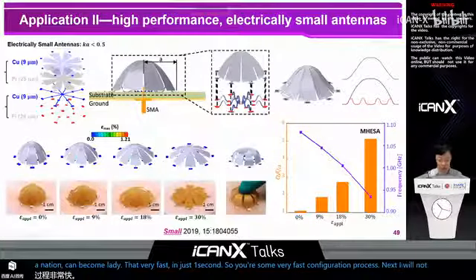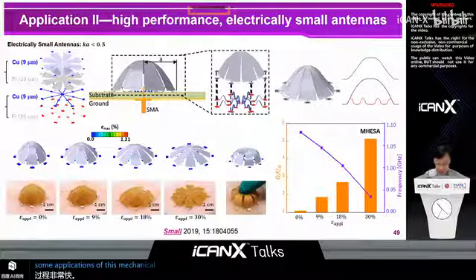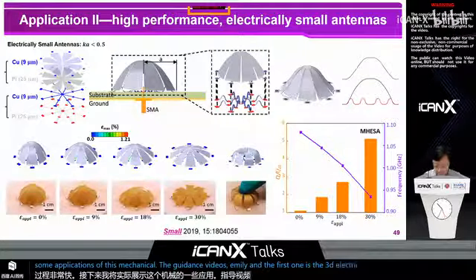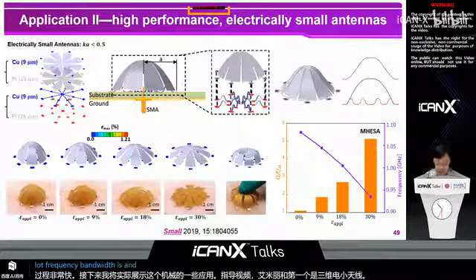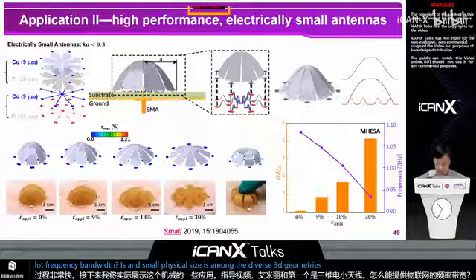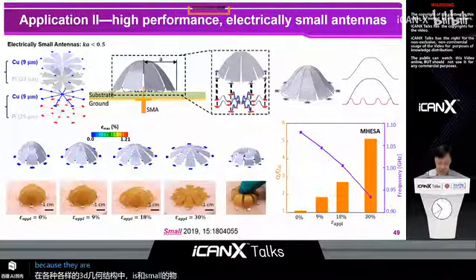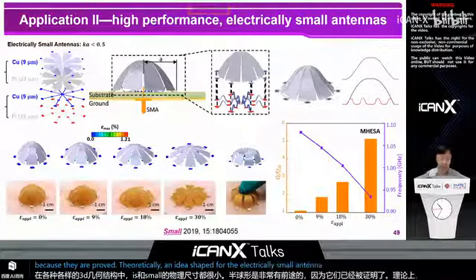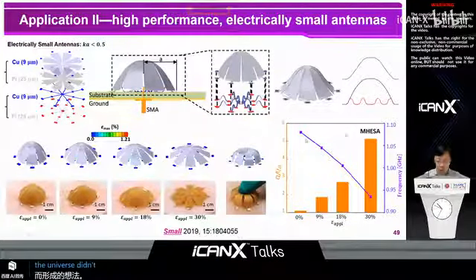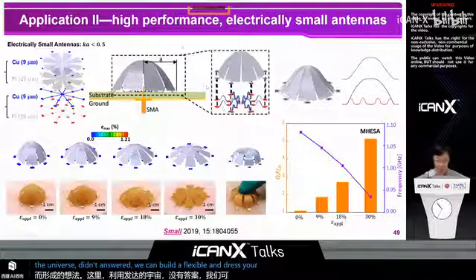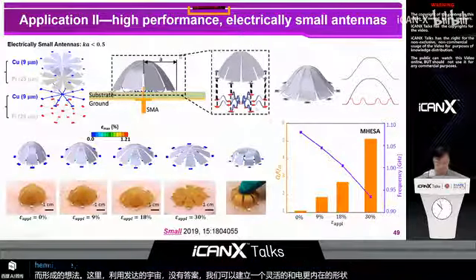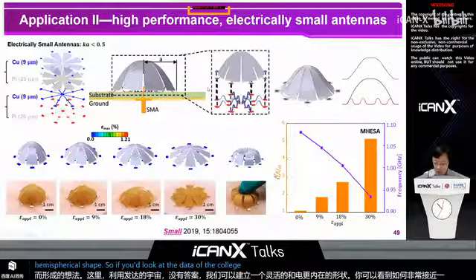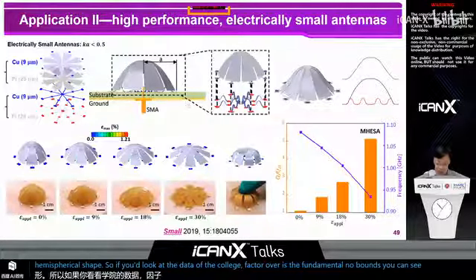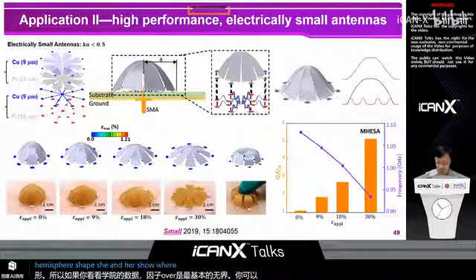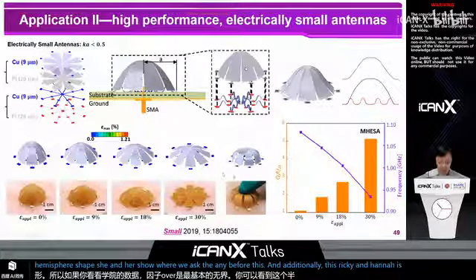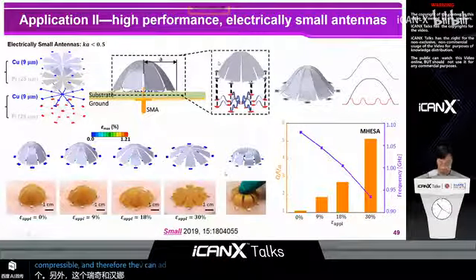Next, I would like to show you some applications of this mechanically guided 3D assembly. And the first one is a 3D electrically small antenna that can offer large frequency bandwidths and small physical sizes. Among the diverse 3D geometries, hemispherical shapes are very promising because they are proved theoretically as an ideal shape for the electrically small antenna. And here, with the use of the developed inverse design method, we can build a flexible and stretchable electrically small antenna with a shape you can see here very close to a hemispherical shape. So if you look at the data of the quality factor over its fundamental lower bound, you can see that this hemispherical shape antenna shows very outstanding performance. And additionally, the 3D antenna is stretchable and compressible, and therefore it can adapt to changes in the environmental conditions.